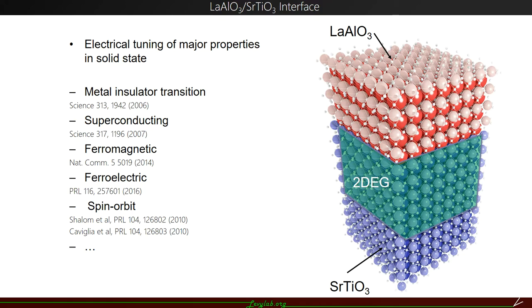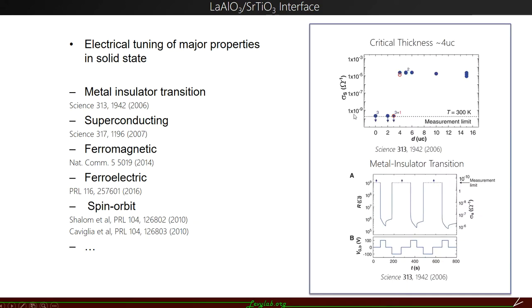In our group, we are mainly focused on one 2D material, lanthanum aluminate strontium titanate, which we call LAO-STO for short. It contains almost all the major tuning properties in solid-state physics, such as superconductivity, ferromagnetism, ferroelectricity, spin-orbit coupling, and so on. Both LAO and STO are insulators, but when we put them together, a 2D electron gas can be formed at the interface when the thickness of LAO is above 4 unit cells. This metal insulator transition can also be tuned by applying a backgate.